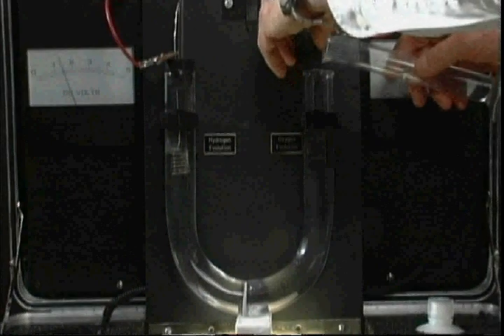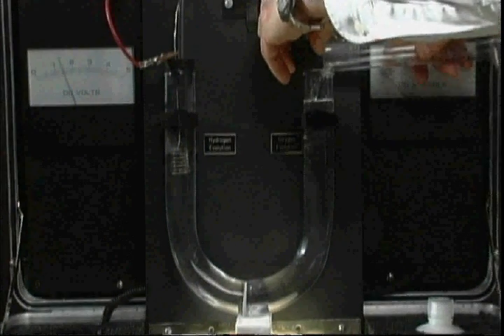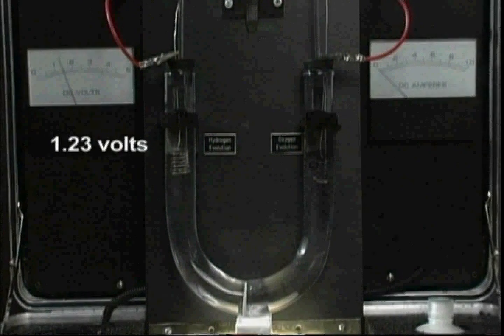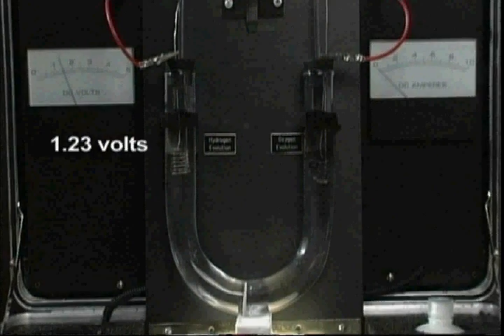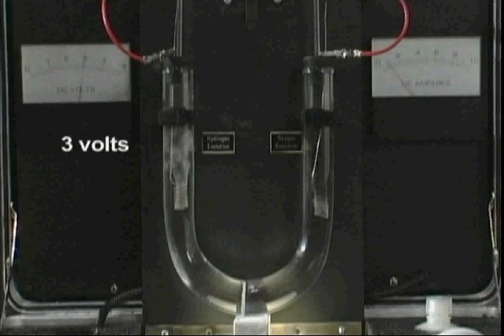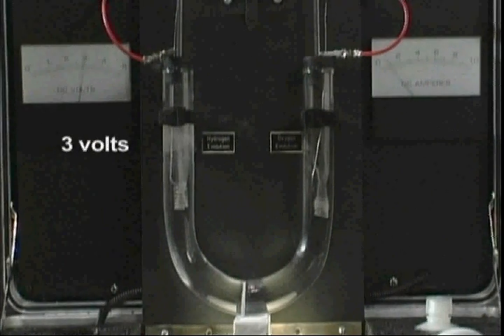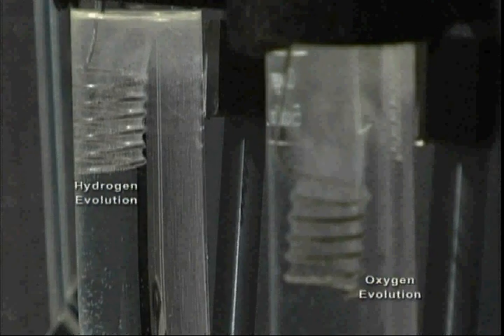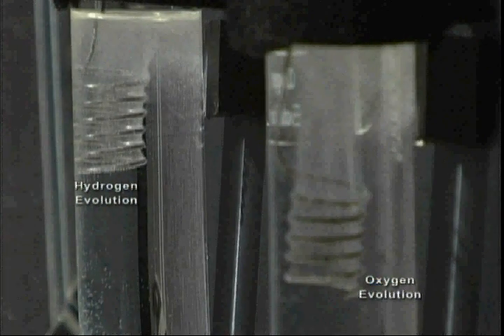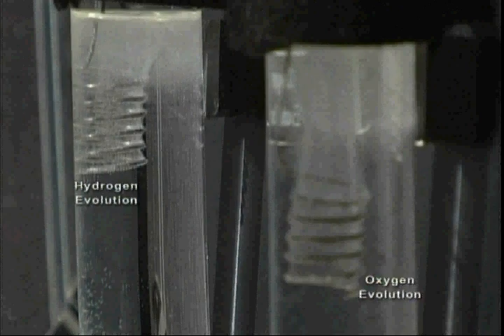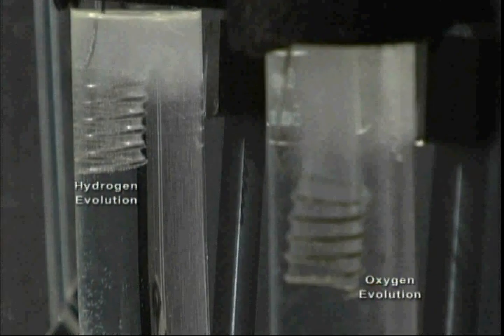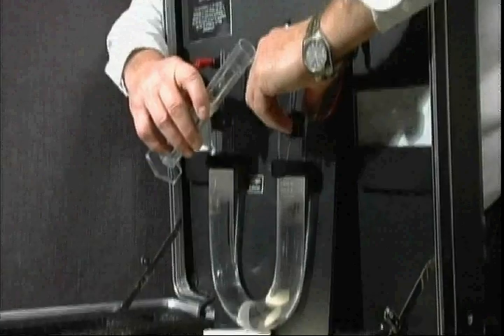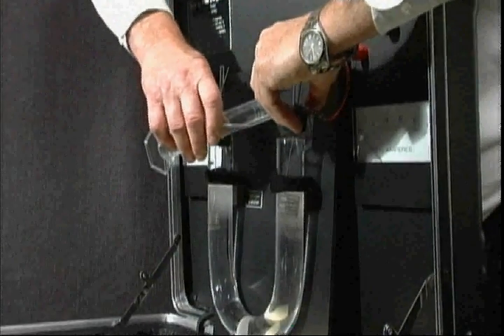Next, I will add some concentrated potassium hydroxide to both compartments. Potassium hydroxide is a very good conductor. Again, at 1.23 volts, we still see no observable evolution of gas. However, as we raise the voltage to 3 volts, vigorous gas evolution is observed at both electrodes. The additional voltage above 1.23 volts is consumed by a combination of internal resistance in the electrolyte and an activation of the oxygen electrode. Finally, I will add methanol to the oxygen electrode compartment.